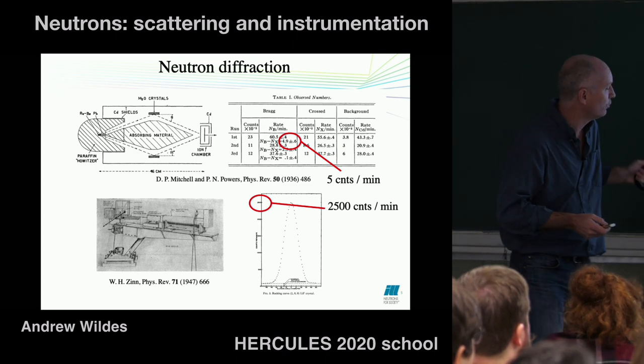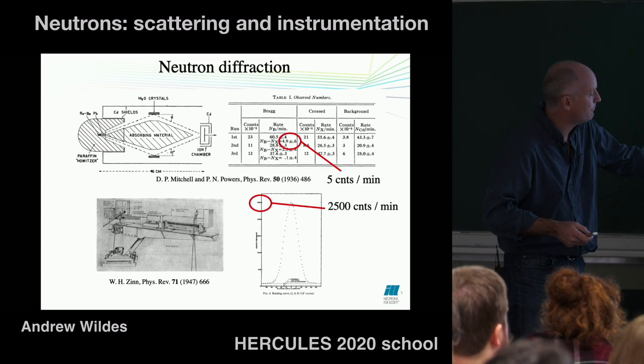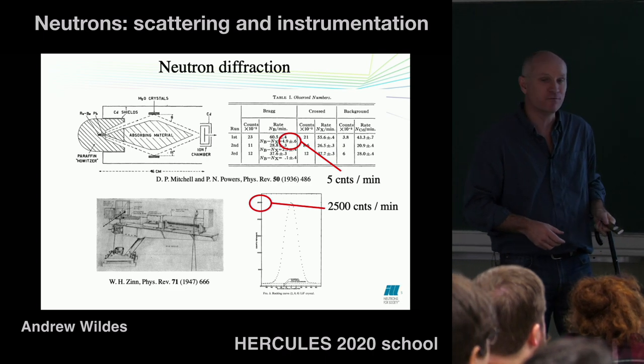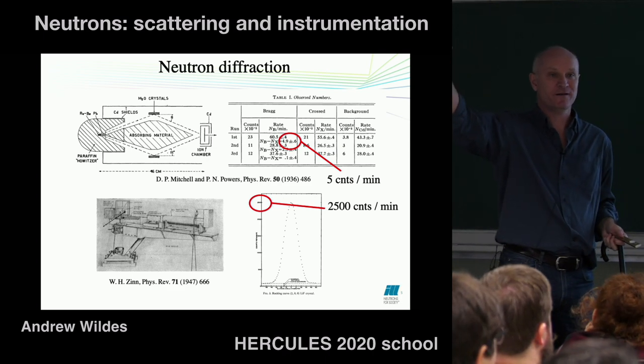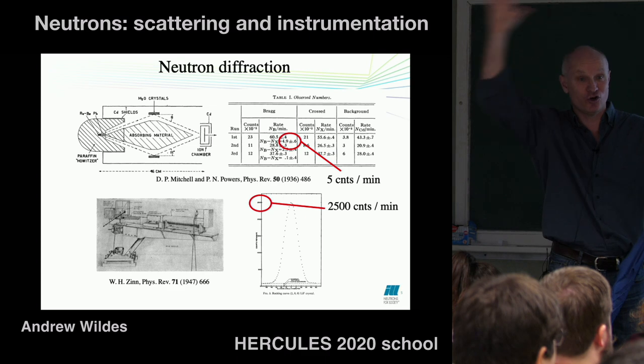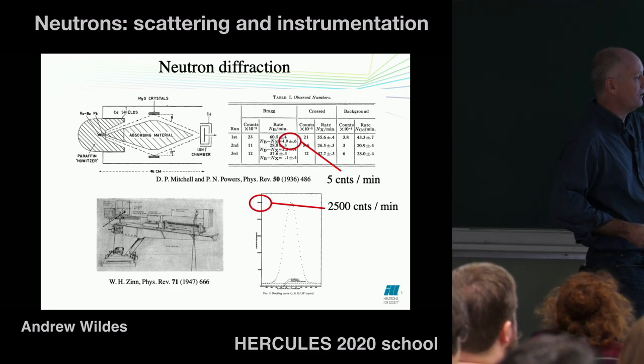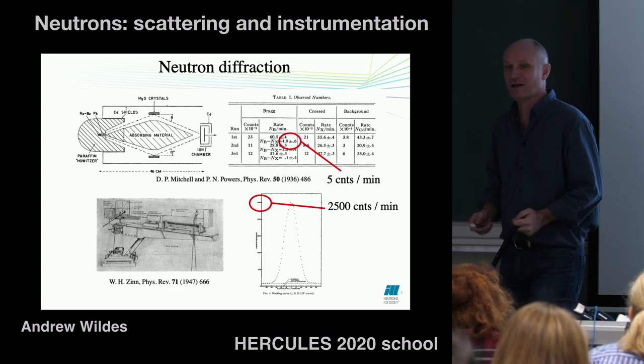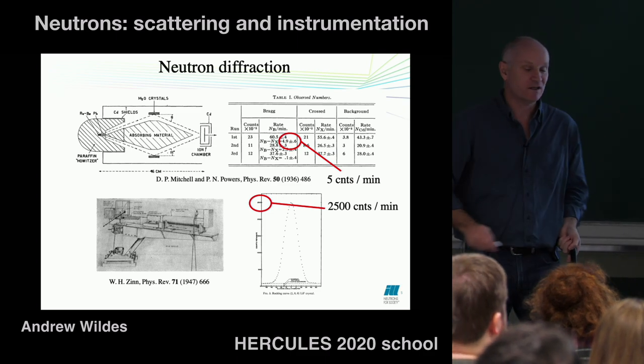And one thing, if you look carefully at this picture, there's a sample in this, and it's a sample of lithium fluoride. It's probably about as big as your fist. That's the size of the sample. So it's a huge sample. And they're still getting 2,500 counts a minute. It's not great, but it's good enough to do this sort of experiment there.